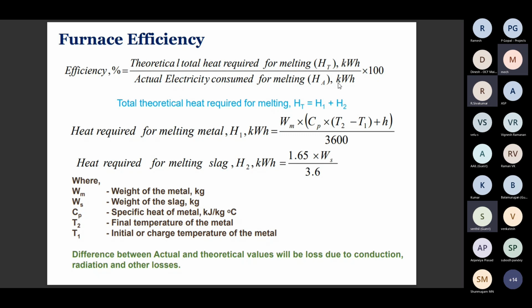If this factor is used, Wm is nothing but the weight of the metal, and Ws is the weight of the slag, and Cp is the specific heat of the metal in terms of kilojoules per kg degree centigrade. Each and every metal, like iron, copper, gold, and aluminum, has some specific heat. It is represented in kilojoules per kg degree centigrade. T2 is the final temperature of the metal. T1 is the initial temperature of the metal. H is the latent heat. By using this formula, we can calculate the heat required for melting the metal. So this is the theoretical total heat required for the melting, and the actual electricity consumed we can note down from the energy meter of the furnace. By substituting these two values, we can calculate the efficiency of the furnace. Next one.